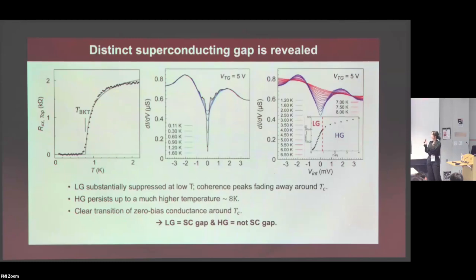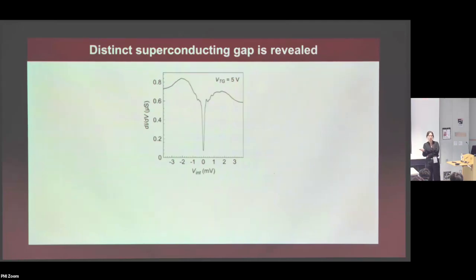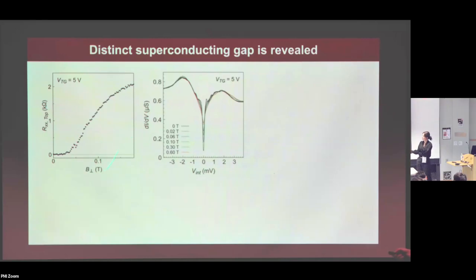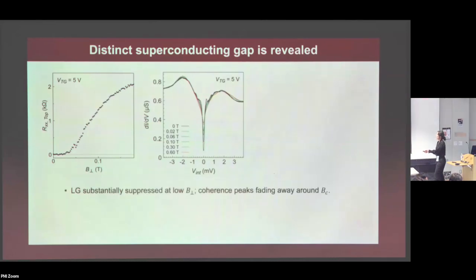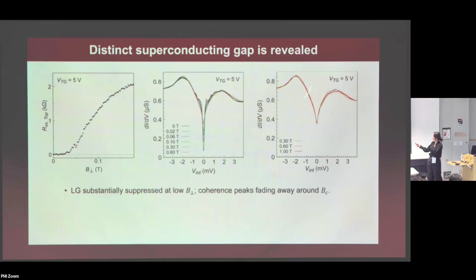But we can't be 100% sure because it's temperature. Who knows what's going on with temperature? So we want to do another check now with the out of plane magnetic field. We can do basically similar measurements with the out of plane magnetic field from 0 Tesla out to like 0.6 Tesla. Again, very similar behavior, and you can compare with the transport measurements. The zero bias conductance immediately gets lifted. These coherence peaks are gone around BC. However, even if you apply the out of plane magnetic field up to 1 Tesla, those high energy gap features, the shoulders, are just very persistently remaining. And I can tell you that in transport devices, there is no device ever reported that has surviving superconductivity even beyond 0.5 Tesla.